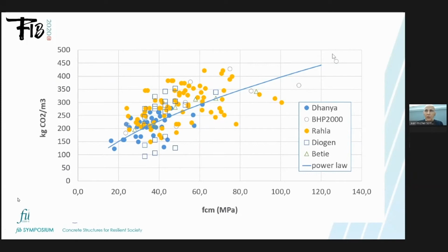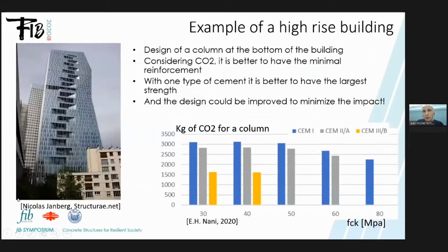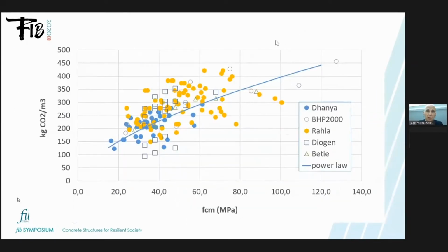And also, it's not obvious that having the lower CO2 emission per cubic meter is the best solution. Of course, if I go back here, you see that the trend is, when you increase the strength, you have an increase of the CO2 per cubic meter. Of course, if you consider a given strength, you could have very large differences, but nevertheless, there is a trend.